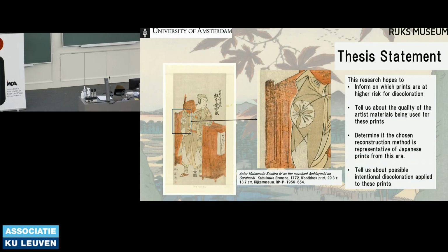So, it has been observed that red lead on Edo-era Japanese prints discolors over time. You can see in this print over here how this red has slowly shifted to black. I chose this research topic because understanding the discoloration of these prints further can inform us which prints are at a higher risk of discoloration, tell us about the quality of artist materials being used in these prints, help me determine if the reconstruction method that I used is representative of Japanese prints from this time, and tell us about a potential intentional discoloration that may have been applied to these prints.